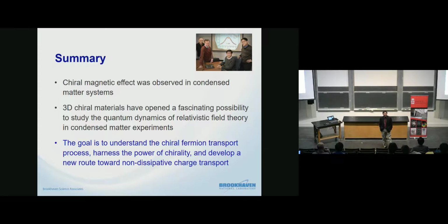Is that what's necessary to really harness it? Yes, well, if it's a single monolayer topological insulator, you probably already have edge states to do the job, right? But if you want to have the whole bulk do the conduction without dissipation, then you go a little thicker, and you go into the 3D transition. So people can study this transition from the topological insulator to the Dirac semimetals by simply tuning the thickness of the samples. Okay, go on.